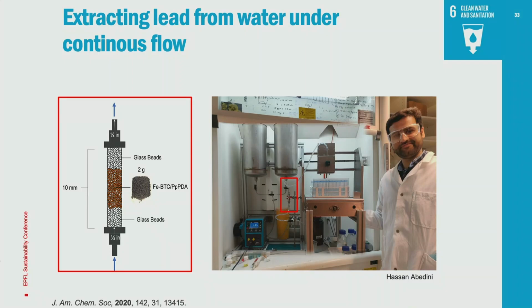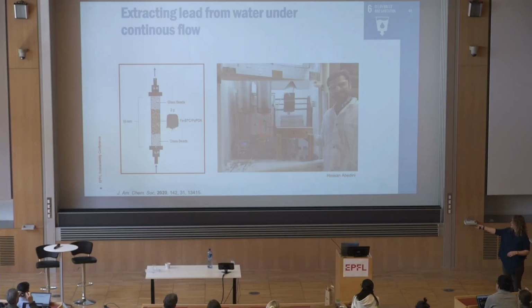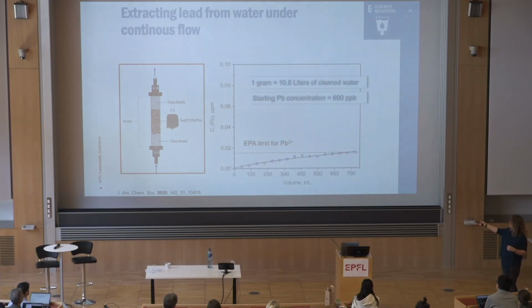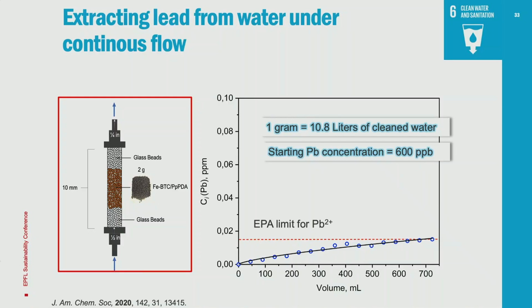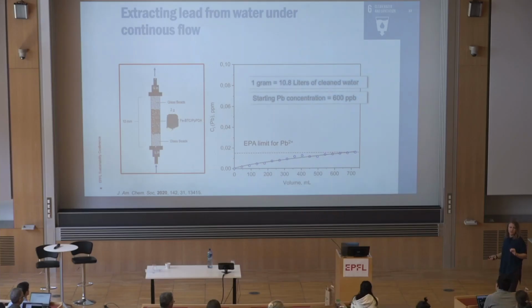So here I'm going to show you the first flow-through experiment. Basically, the contaminated water goes through, comes out the other side. Okay? And we're monitoring on the back end what's coming out, right? So here I'm just showing you the lead concentration. You can see it's gradually going up. We're measuring the concentration on the back end after it's gone through the column. And then we cut the experiment off after we reach the EPA limit for lead. Okay? So this is where it's no longer deemed drinkable, so to speak.